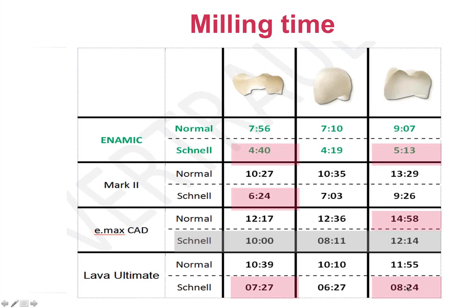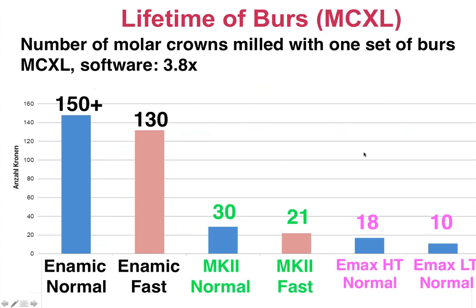So you may wonder, well, Lava Ultimate also has a lot of polymer in it. Why isn't milling as fast as Enamic? A polymer material should mill fairly quickly. The diamonds actually become clogged with the high polymer content in Lava Ultimate, whereas in the Enamic, the polymer helps facilitate the burr cutting through the material, and then the ceramic network facilitates cleaning out the diamond burr, so it actually sharpens the diamonds as it's cutting. So you've got, again, best of both worlds between the ceramic network and the polymer.